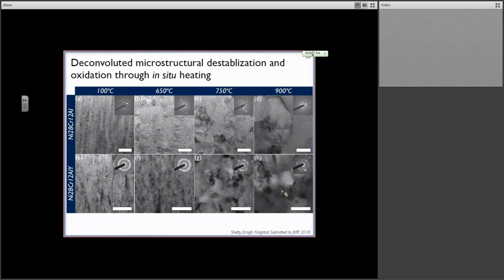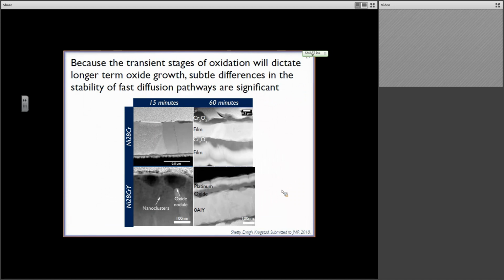But to come back to this idea of oxidation behavior, and really tie this story together about how we can actually manipulate oxygen scale formation by playing with a microstructure, we look at the comparison here, wherein for the yttrium-free thin films, at 15 minutes we don't have the microstructure we started with. We have the oxide that is along the top, it's still discontinuous.